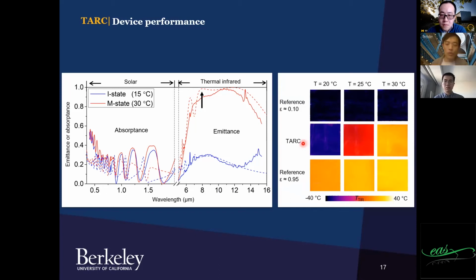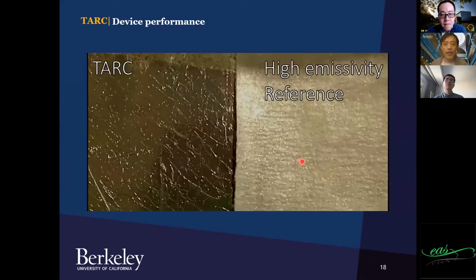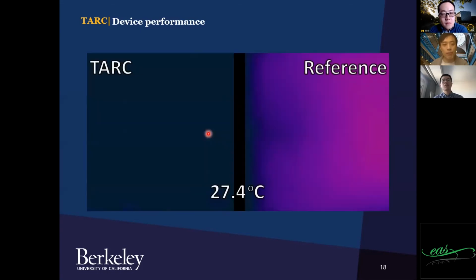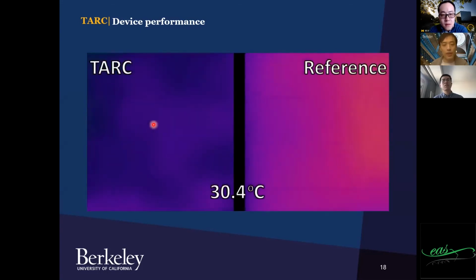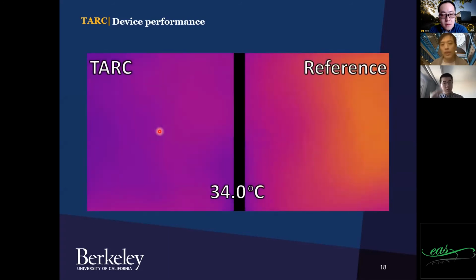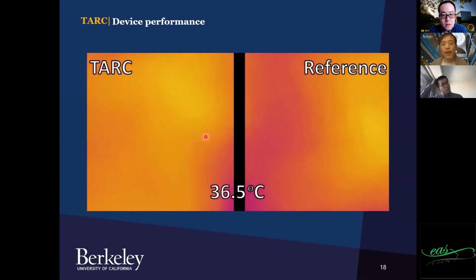So we use that to measure the temperature of TARC. When the TARC's temperature is cold, the readout is really small, close to the aluminum foil. When the temperature is high, its readout is close to the tape. That's what we expected. And this is a video that shows this change. The left-hand side is TARC, the right-hand side is a high emissivity reference. And by increasing the temperature, you can see at first the TARC has a small readout, and finally its IR temperature matches that of the reference.